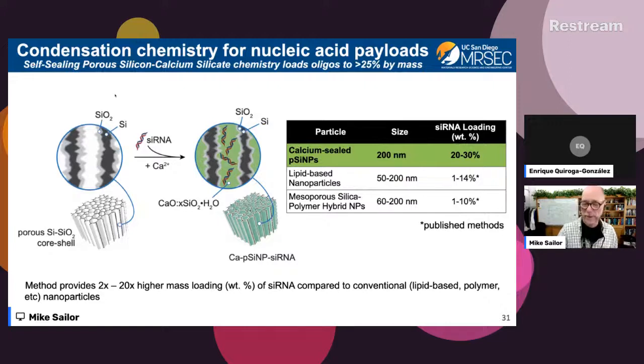So for example, shown here in the green, the calcium ion silicate sealing chemistry that we use for siRNA gets us somewhere between 20 and 30% by mass loading. So already that's 1.5 to 2 times more drug loaded into the nanoparticle. And in this business, even doubling the amount of drug that's in the nanoparticle is a big deal.